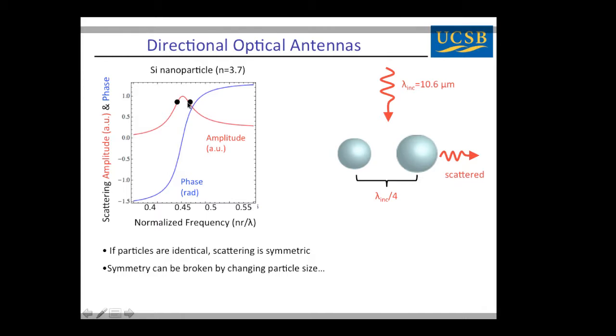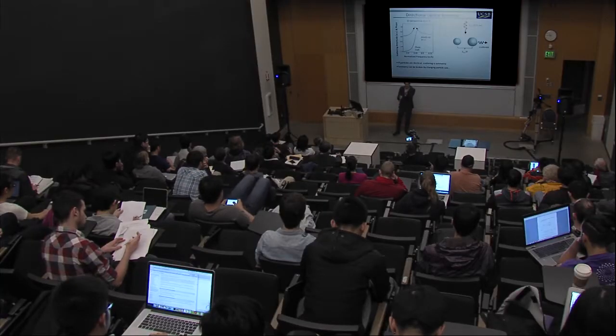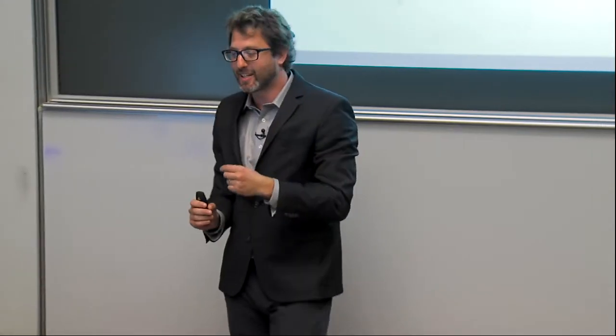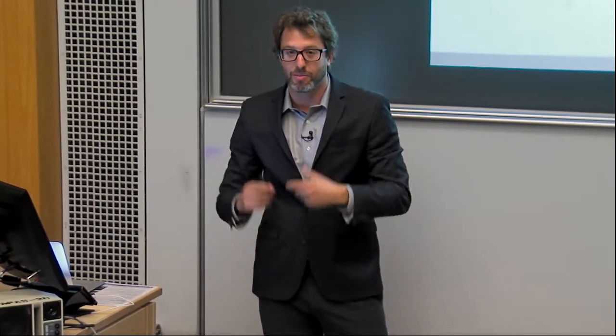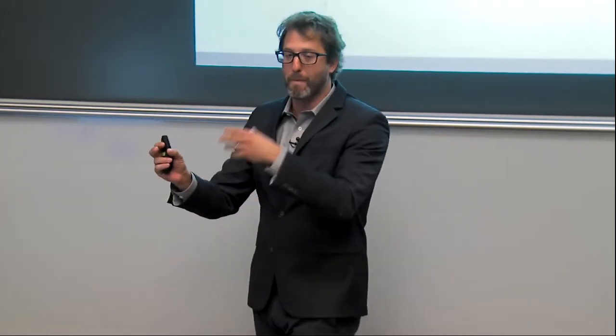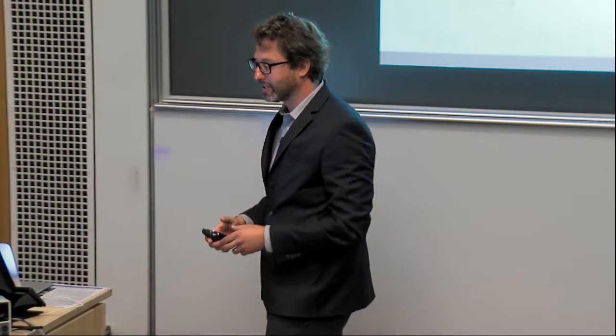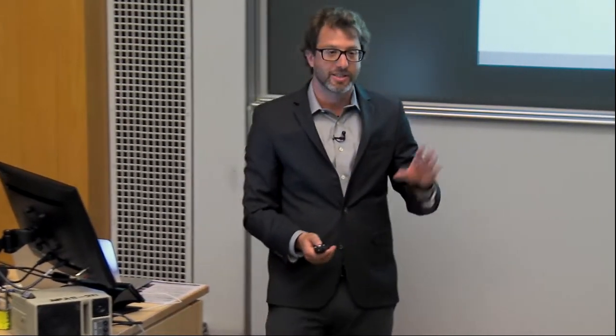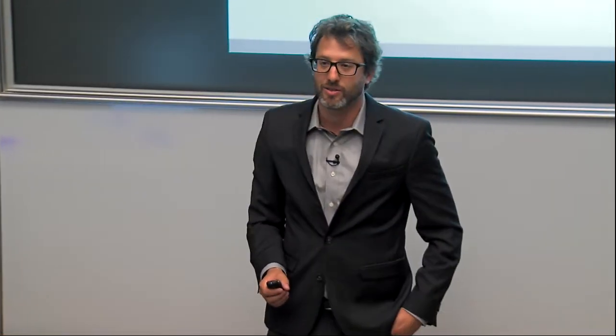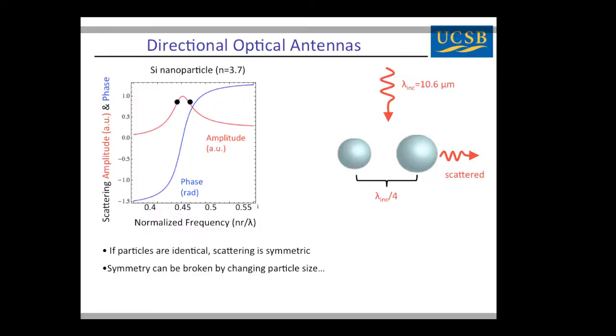So they have equal amplitude, but if we look at the intersection with the phase curve, they have a pi/2 difference in phase. Okay? So this pi/2 difference in phase, when coupled with the spacing that gives us a pi/2 propagation phase, can either add up destructively, pi/2 plus pi/2 is pi, so that's a destructive interference, or constructively. If I have pi/2 minus pi/2, that's 0, they're in phase. So we would get out of a system like this a directional radiation lobe pointing to the right.